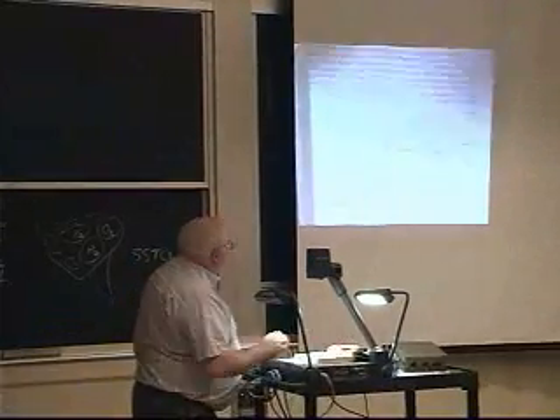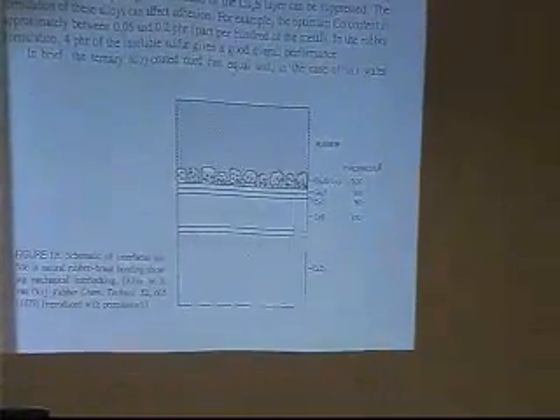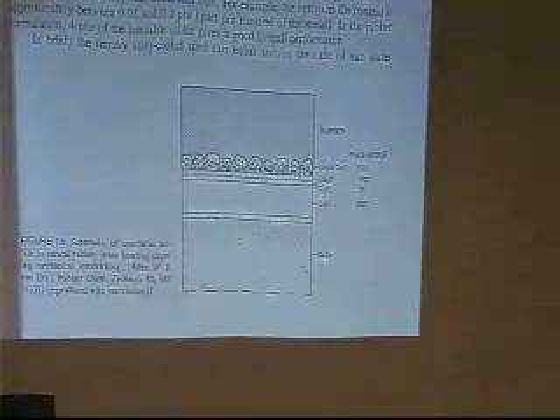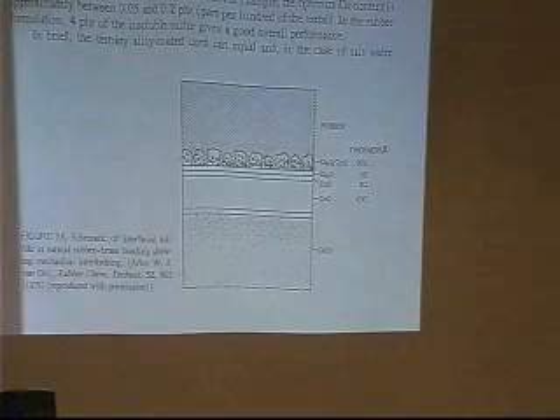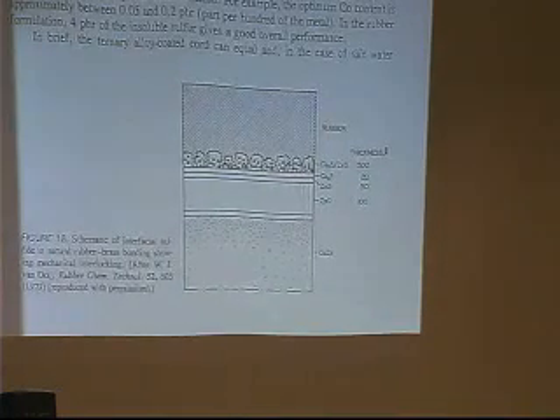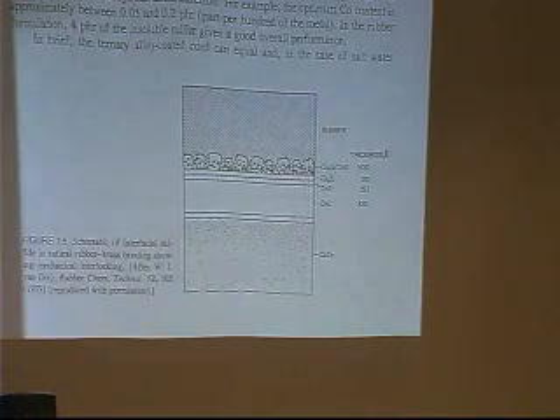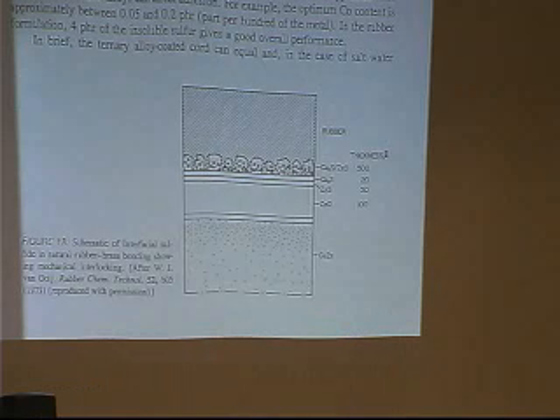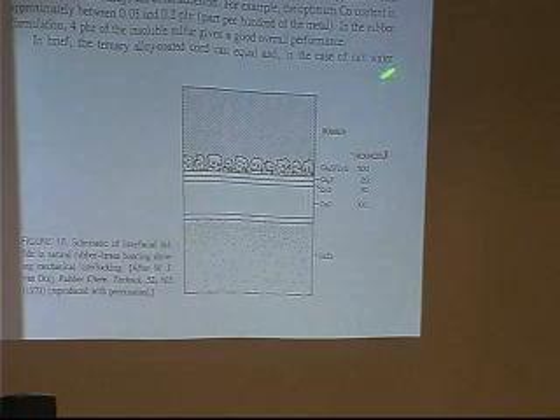And that's what we call type 2. This gives you an idea of what happens in tire cord. Okay? If you drive on steel belted radial tires, right? You've got to bond rubber to the steel cord. If you don't, the thing's going to delaminate. You lose your tire tread, and the steel cord doesn't do you much good. So when they first started doing this, they were just trying to bond rubber to steel. And it can be done, but it doesn't work very well. And they found if they plated it with copper, they got a much better bond.